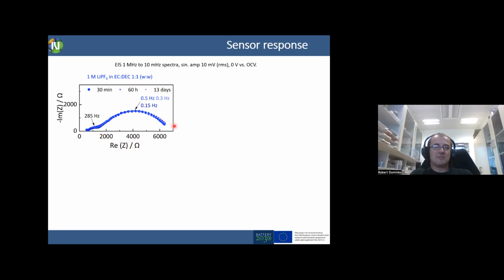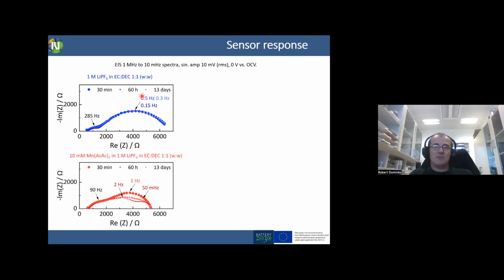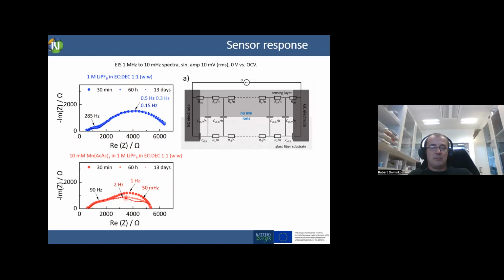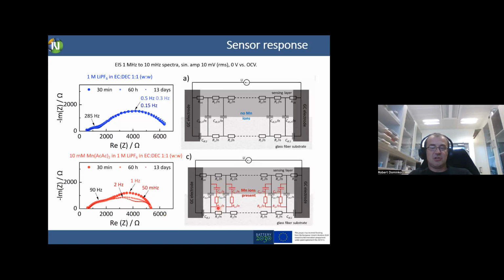And actually, what we can see, if we are using electrolyte without any additional manganese inside, we see in impedance spectra a repeatable result for 2 weeks. But once we put manganese into the electrolyte and repeat the same experiment with the sensor that has the sensing layer inside, we see some deviation in this mid-frequency region. And that actually corresponds to some additional capacitance and resistance, which is parallel to the sensing layer and glass fiber substrate, and it can only be due to the presence of manganese ions inside the electrolyte.